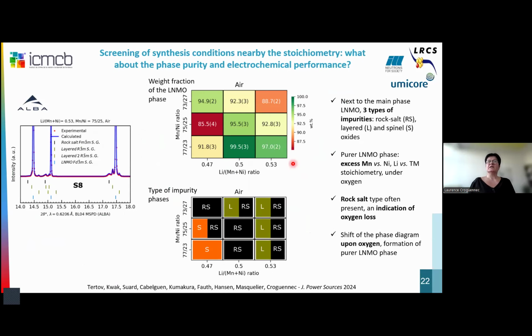So here, I just wanted to highlight the fact that it's really thanks to a synchrotron X-ray diffraction pattern that we were able to use to identify the impurity, at least from a structural point of view, and to identify the presence of rock salt impurity, as often observed in that kind of materials, but also of different layered oxide impurities. You can see different peaks associated here in the background.